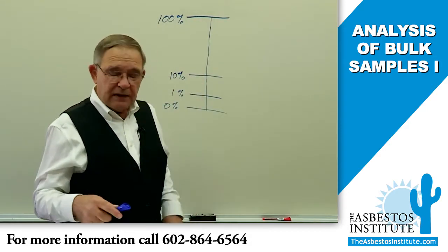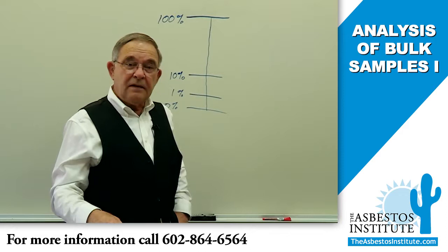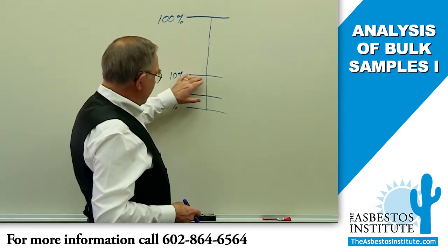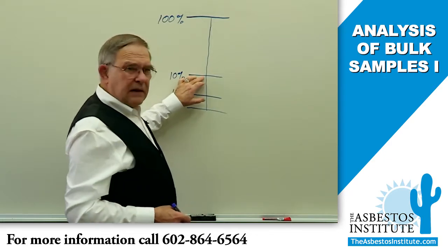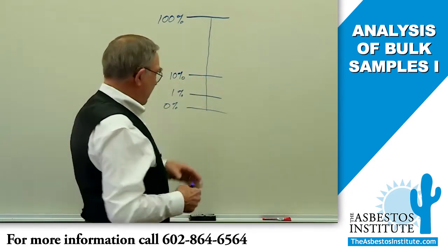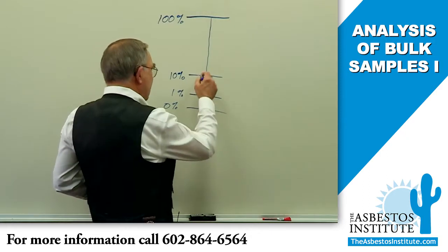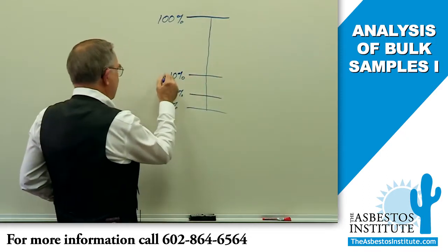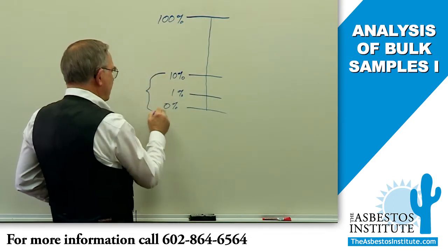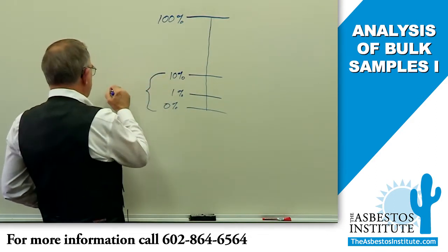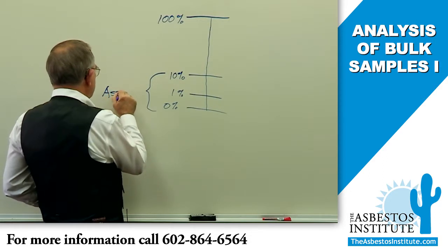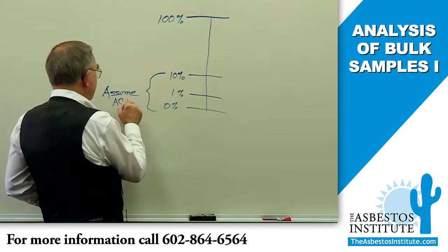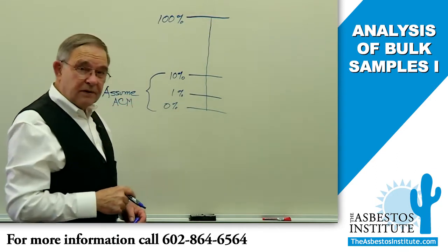So EPA recognized that early on in this regulated industry, and they said, okay, below 10%, the safe thing to do is just assume positive, okay? So any level below 10%, this area right here, we assume positive. Assume ACM. Assume that it's greater than 1%, okay?